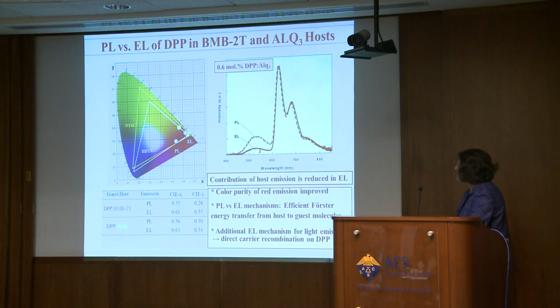So using these compounds, I show you now the color gamut. In order to get the pure red, pure green, and pure blue, you want to be at the apex of the triangles. So this is pure red, pure green, and pure blue. And we succeeded in getting very good red OLED based on this pentacene derivative.